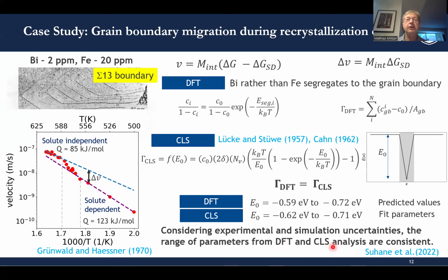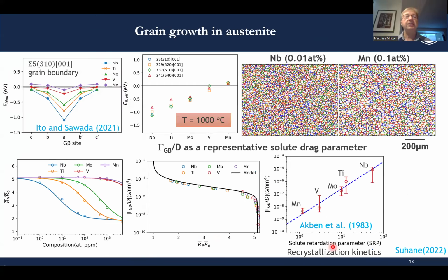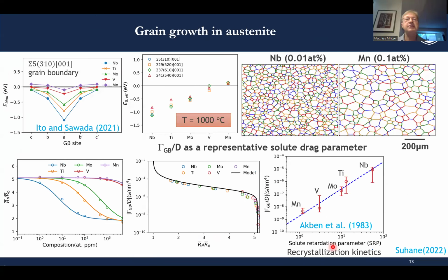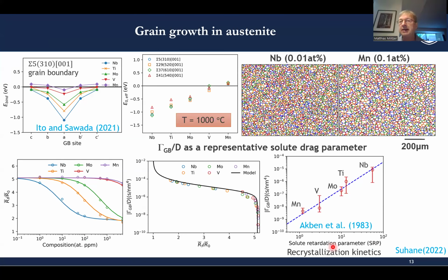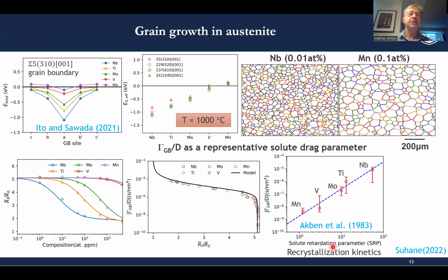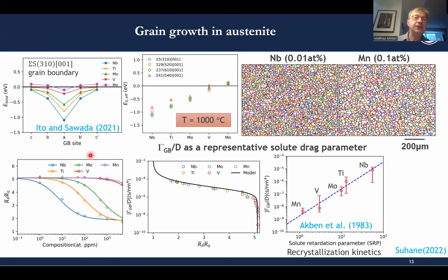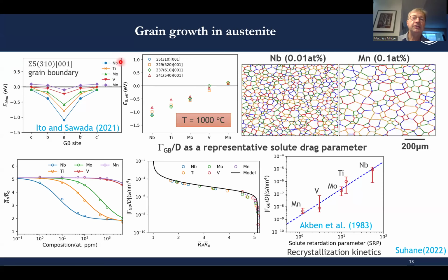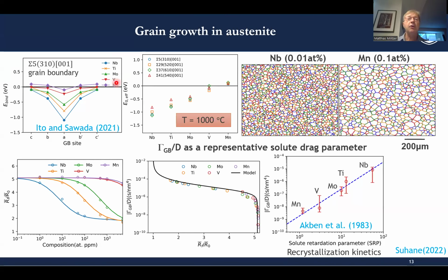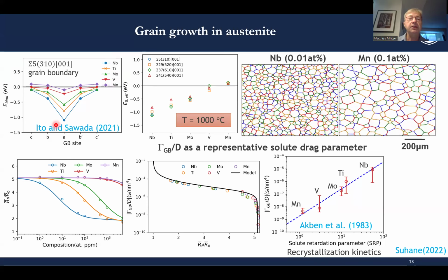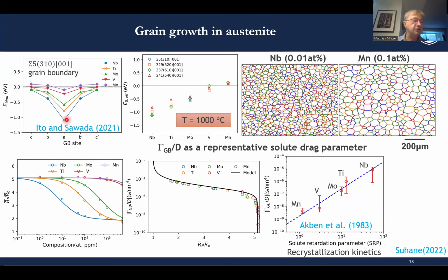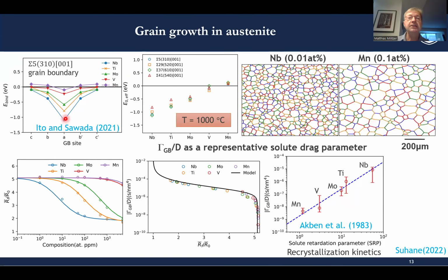And we use this approach now to make alloy predictions. And I will show you some results for austenite grain growth in steels. Ito and Sawada from Nippon Steel had done a wide range of simulations for different sigma boundaries in FCC iron to find out what the binding energy of important alloy elements in steels would be. I show you here results for sigma 5 grain boundary with niobium, titanium, molybdenum, vanadium, and manganese. So these are binary systems that are being considered. And that's the order of the depth of the potential well. So niobium has the strongest binding energy, followed by titanium, molybdenum, vanadium, and manganese.